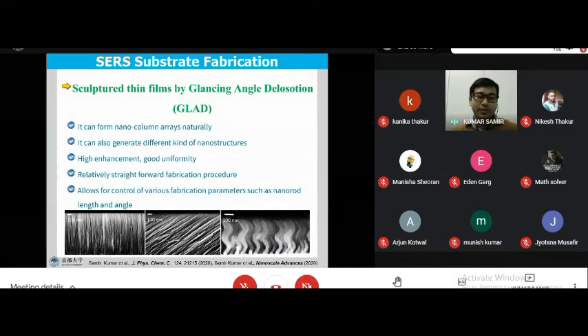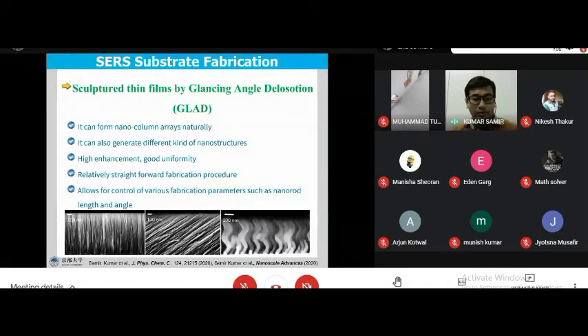So my research focus is on the fabrication of such substrates by glancing angle deposition. The thin films fabricated by this glancing angle deposition are also called sculptured thin films. They are called sculptured thin films because we can tune the morphology of these thin films during the growth itself by changing the rotation, the speed or the angle of the substrate during fabrication. And we can grow different types of nanostructures like vertical columns, slanted nanocolumns or zigzags.